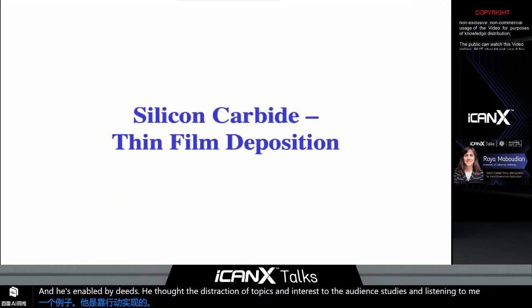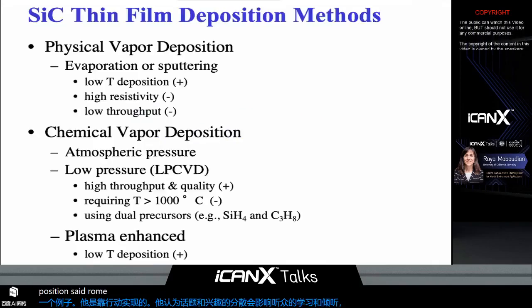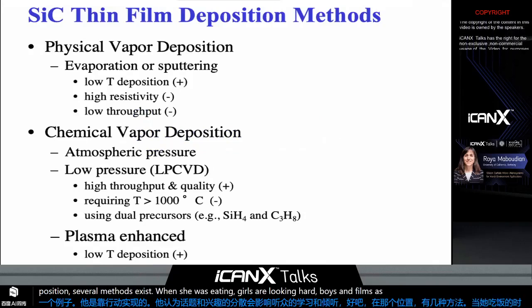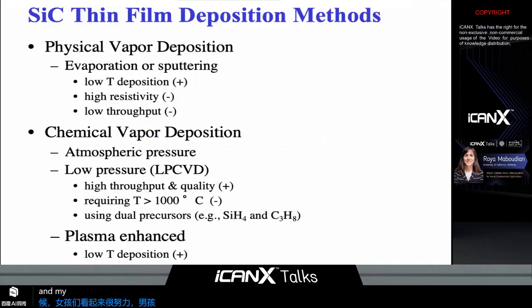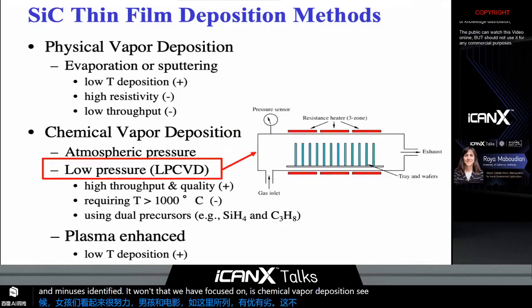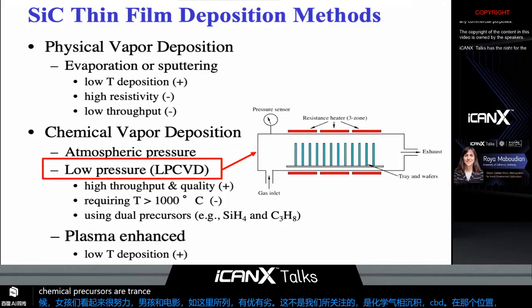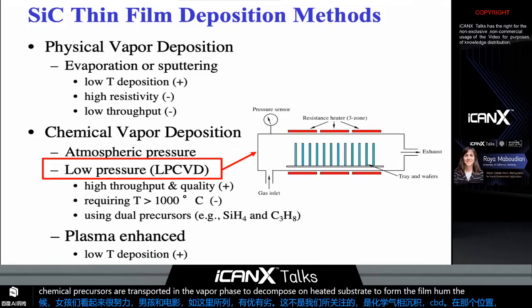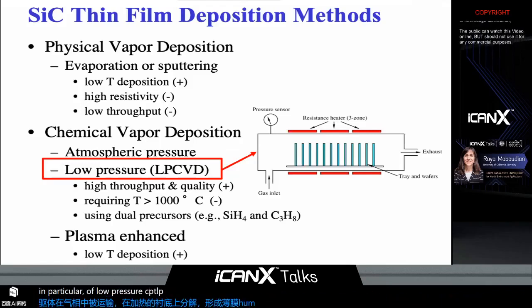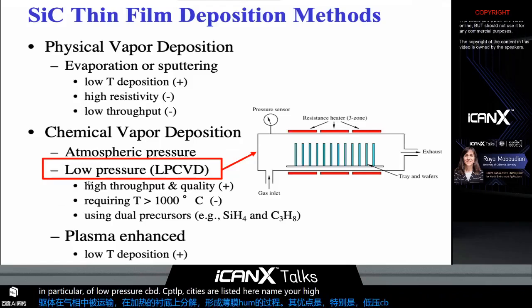Okay. Thin film deposition. Several methods exist for depositing silicon carbide thin films, as listed here, with their pluses and minuses identified. The one that we have focused on is chemical vapor deposition, CVD. In addition, chemical precursors are transported in the vapor phase to decompose on heated substrate to form the film. The advantages, in particular, of low pressure CVD, LPCVD, are listed here, namely high throughput and high film quality.